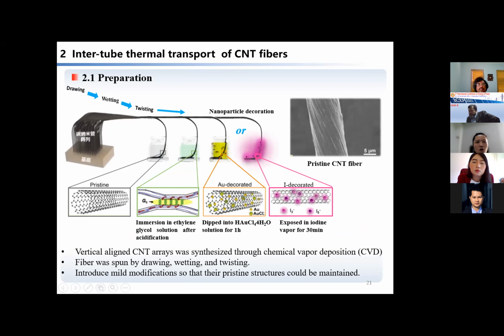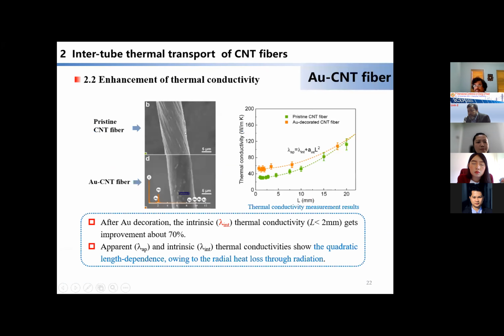Gold nanoparticles or iodine: dip the fiber into the metallic salt solution or expose it to iodine vapor. We can see from our test that this modification maintains their pristine structures. This is pristine CNT fiber. We can compare it with after decoration.